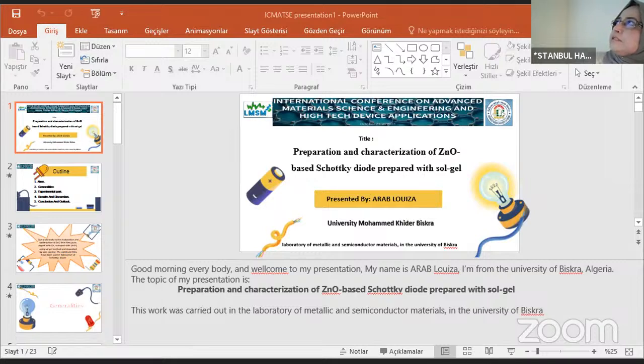So this table summarizes the value of the sheet resistivity, the conductivity and the resistivity for ZnO doped. We can't say pure, logically we say doped. There is no pure zinc oxide, and ZnO doped with gallium 4% and co-doped with aluminum and indium.